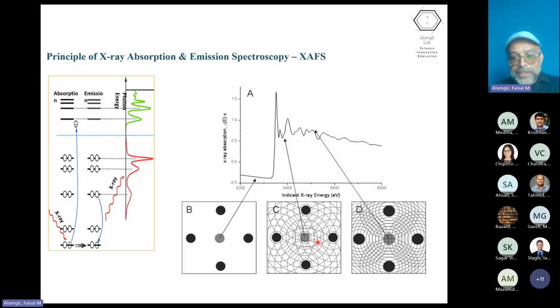You see, the returning wave can either be in phase or out of phase with the absorbing atom or anything in between. So the fact that the returning wave oscillates between being in phase and out of phase over and over again is the reason why we get these oscillations here. So in other words, we're getting multiple snapshots of pictures of the structure around the atom, and the larger this range of information we capture, the more clear that picture becomes, right?